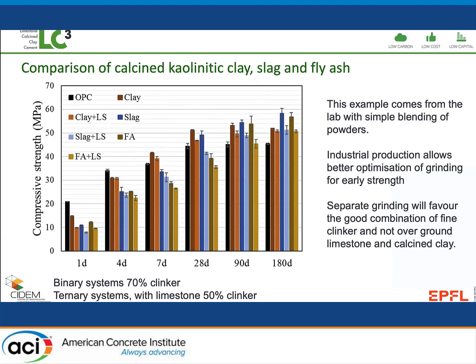So in terms of performance, if we compare to existing substitution materials like slag and fly ash, we see that in the long term, these mixtures, and we did two types of mixtures. We did binary mixtures with 30% of the SCM, and then we did these ternary mixtures with the SCM and with the limestone. You can see at long term, they're all pretty similar, but at early ages, the calcined clays always have the highest performance.